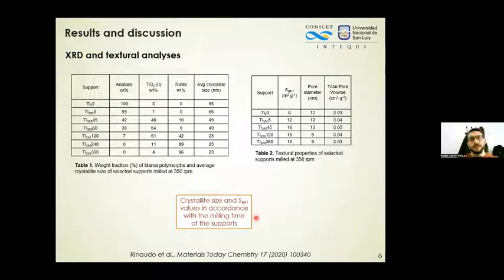And this is like that because the milling time and the structure made in the milling could define the particles and therefore, as a consequence, increase the surface exposed. So we have lower crystallite sizes and an increase in the surface area, as you can see here. And we could double this starting value of 8 square meters per gram with the milling time,